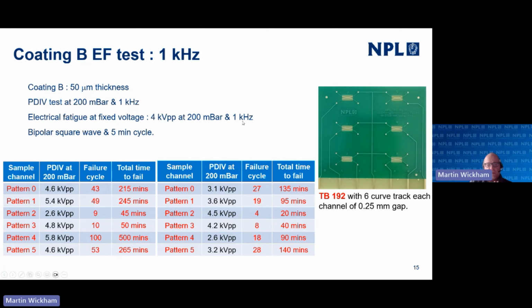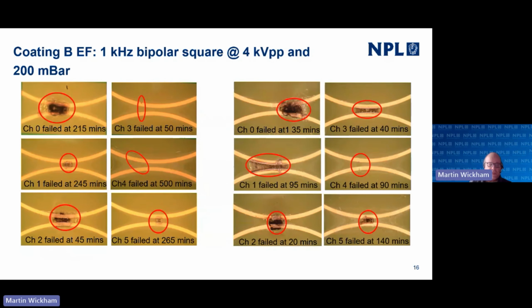And at 1 kilohertz, 4 kV, 200 millibar, we're failing somewhere in the region of 20 minutes to 500 minutes. And there's obviously a distribution here because we're primarily looking at defects within the coating, and all the defects are not exactly the same across all these samples. So each sample differs slightly from the next. That's why we get a distribution in failures.